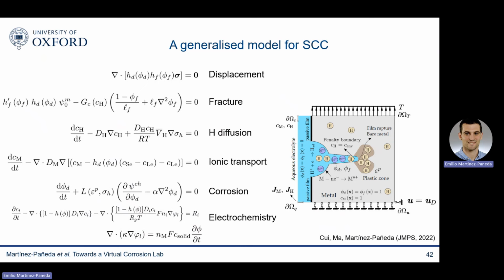In this way, we can present a generalized model for stress corrosion cracking, where we don't need to make any assumptions on whether damage is anodic dissolution driven or hydrogen driven. We simulate everything that is happening and let the model decide, let the model pick the mechanism. So all the electrochemomechanical machinery that we had before, we now add a second phase field to describe the behavior of cracks. We predict the uptake of hydrogen to the metal by adding to our electrochemistry model the hydrogen evolution and absorption reactions. And we model the transport of hydrogen within the metal and the embrittlement process, the fracture of the metal due to hydrogen.